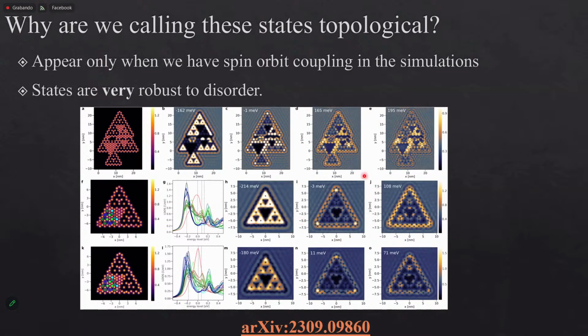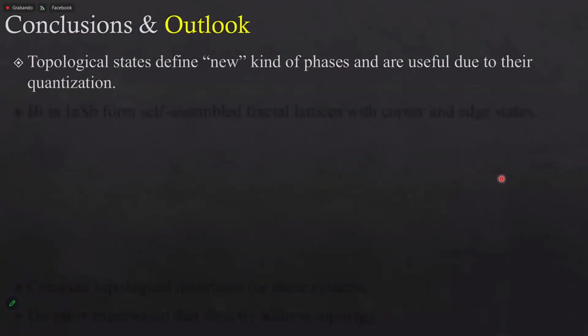For this value of disorder, things are a bit difficult to see, but I can show you some values with more disorder. And you see that the bulk is completely destroyed. You see more localized states, but they're not really uniform, while the states really remain at the edges of the system. So it's a very strong sign that these states are topological. So this is more or less what I wanted to talk to you about today.